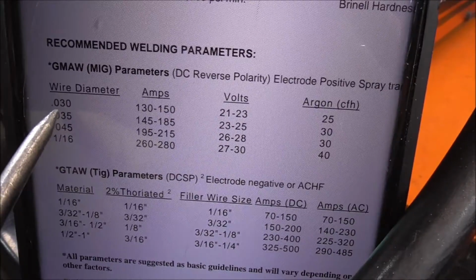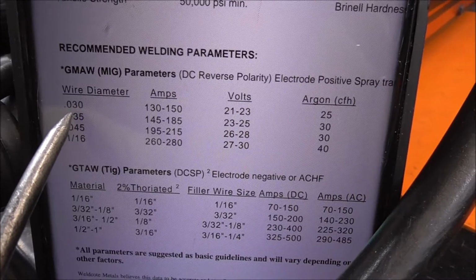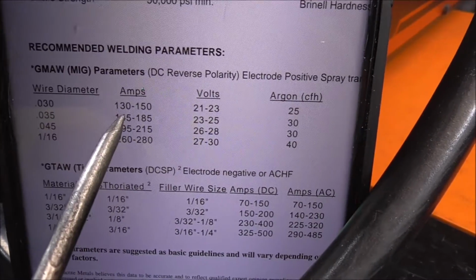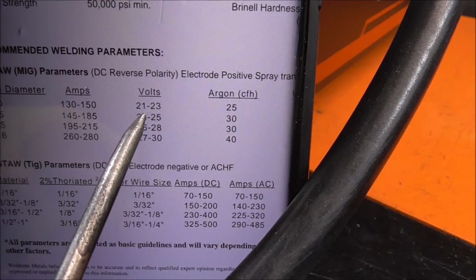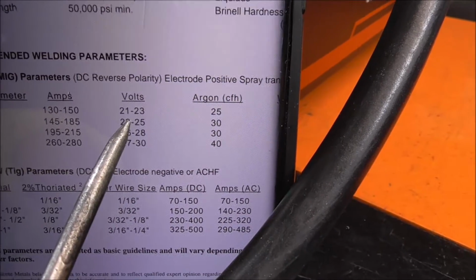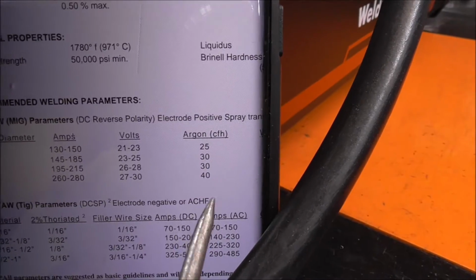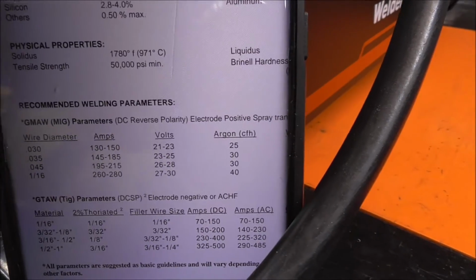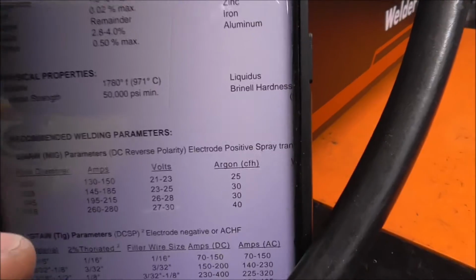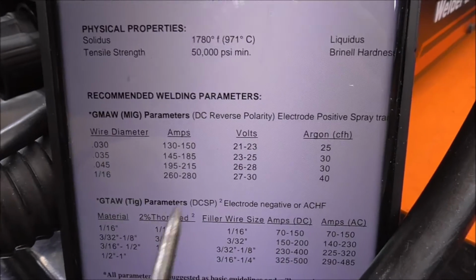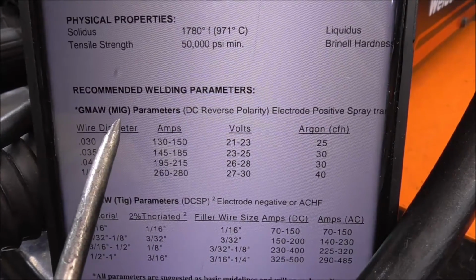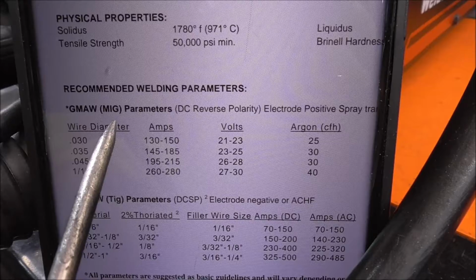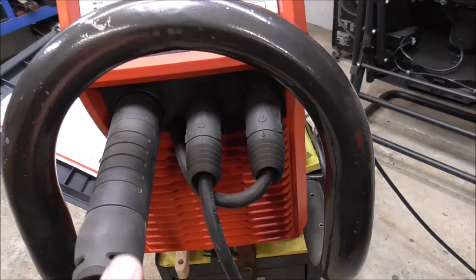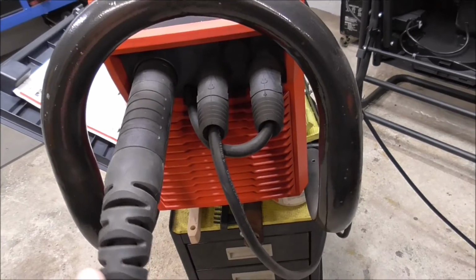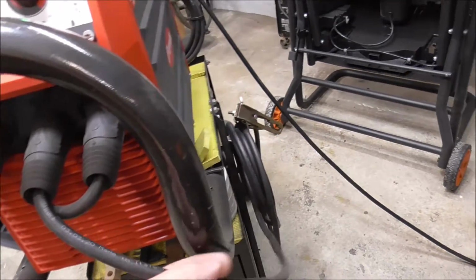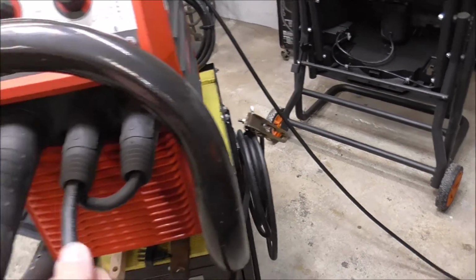It's saying the recommended parameters for .030 wire is 130 to 150 amps, which is 21 to 23 volts. That's what we're using. We're using pure argon. Those seem a little high to me, but it is what it is. I'm not going to argue with the experts. They know more about it than me. These are the recommended welding parameters for MIG. And we are on the right polarity, DC electrode positive. Your MIG gun is going to be positive, and your ground is going to be connected to negative.